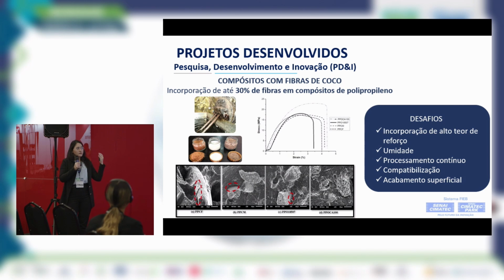So when we do the processing of composite, we have issues from the feed stage because the fibers get tangled, and that's hard in the input process in the extrusion. There might be a high humidity content, so we have to be concerned in the pre-processing. We need to properly dry the fibers. Another issue during the extrusion processing, that's the continuous processing. If there is a lump of fibers in the polymeric matrix, we cannot pull the material. So we need to be careful in the feeding process.